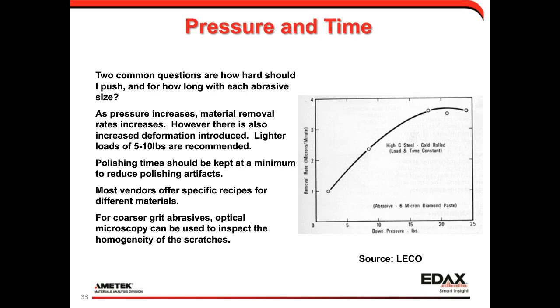A common question I get is, how hard should I push when doing this and for how long? The general rule of thumb is that as you increase the pressure, your material removal rate increases, but at the same time you introduce more deformation. So generally I use lighter loads, aiming for 5 to 10 pounds force on a sample, and I'm generally using 1 inch to 1 1/4 inch samples in my polishing procedures. And so I generally like to polish for minimal times. It's all relative, to reduce artifacts.